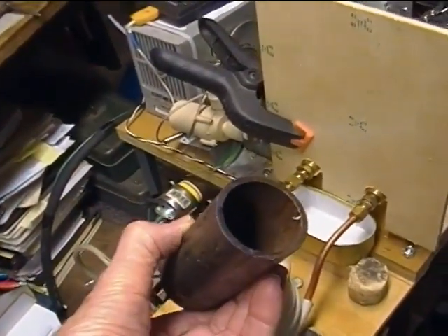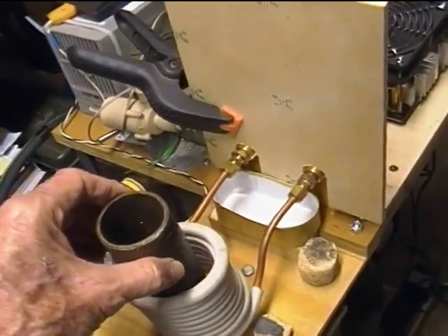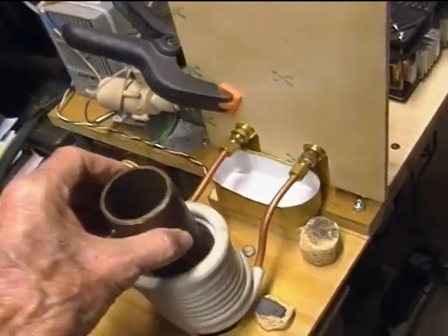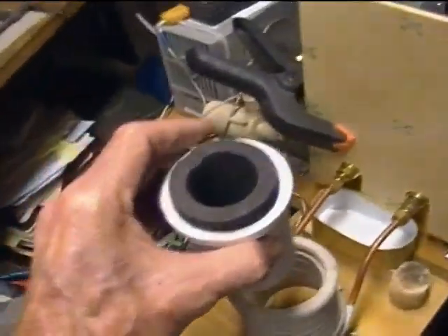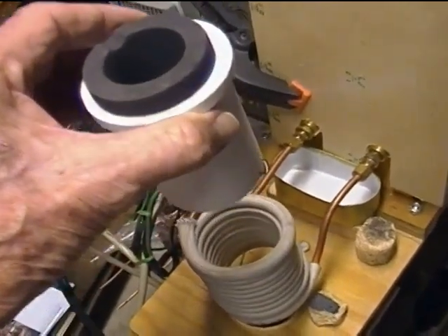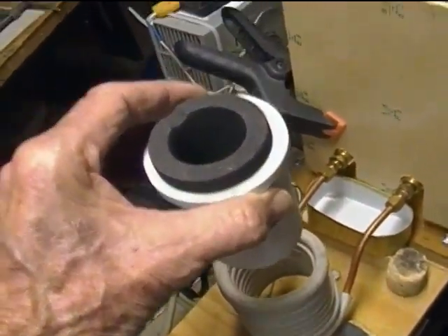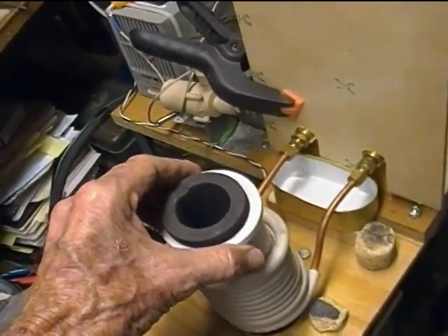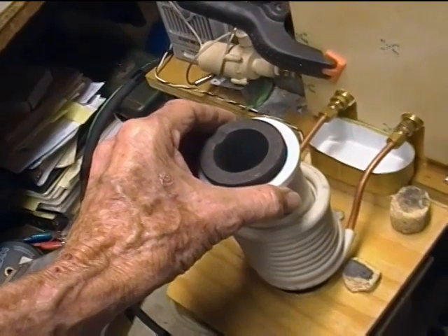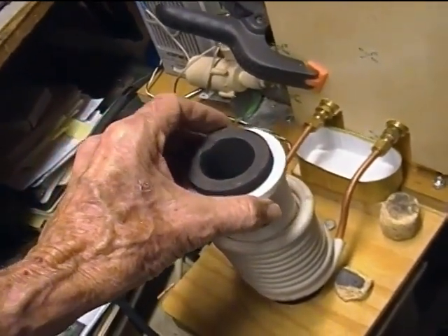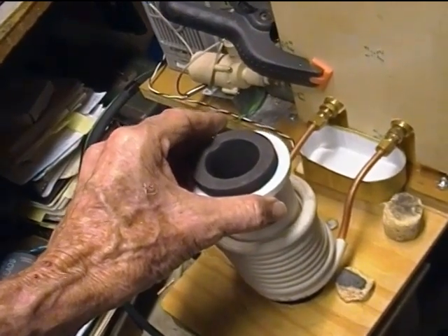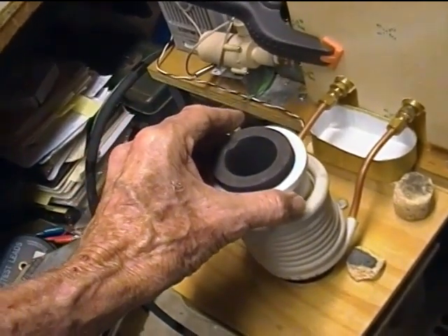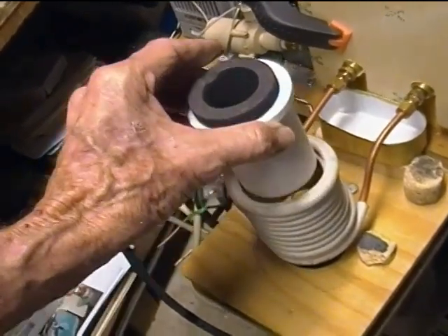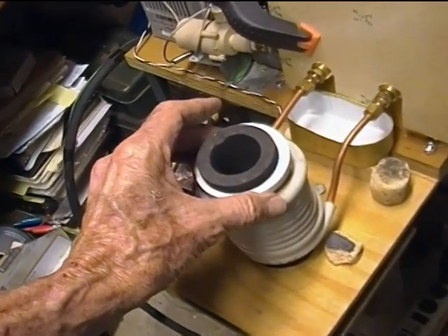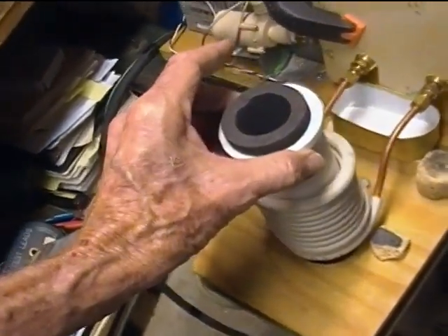On the other hand, if you've seen my other videos, if I put this steel piece of tubing in there, I can't stick it down there very far at all without it exceeding 50 amps on its own. So what's going to happen when I have this thing full of cold or below Curie point iron when I stick it in here? I suspect, and we will get to see, you and I for the first time, what happens as I try to stick this combination of crucible, which is capable of 30-40 amps all by itself, and iron, which is capable of 30, 40, 50, 60 amps all by itself down in the crucible. So since I don't want to blow up my setup, but I do want to actually try to melt some cast iron,